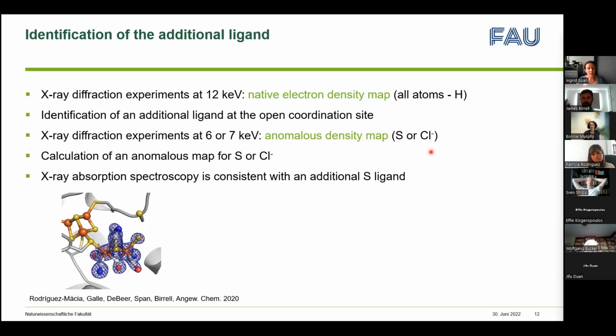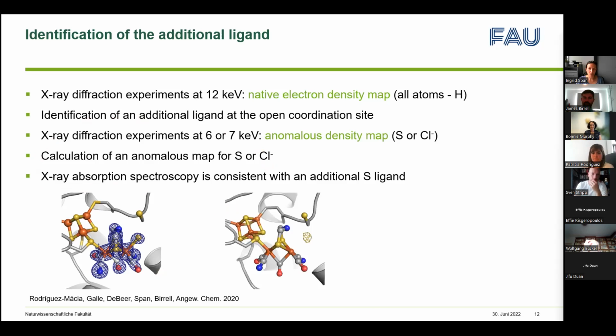So we can calculate an anomalous map that shows the substructure of either sulfur or chloride at the same time. So we cannot distinguish between these two elements. However, we combine this with other techniques, and especially X-ray absorption spectroscopy was also consistent with the presence of an additional sulfur ligand. So this is the anomalous density map, and I only showed this for this extra ligand.